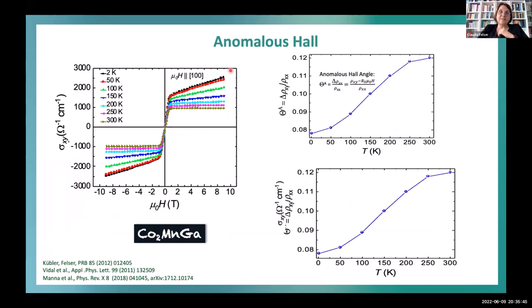So we have this linear kind of behavior here, and here we have the resistivity rho xy versus the magnetic field. And from the first view, it looks like a hysteresis, which everybody has probably already measured in something like iron in a SQUID. So you see this hysteresis loop, and it's a soft magnetic material, so we don't really have hysteresis. It's very soft, the Heuslers, because they are cubic. And you have this normal contribution to the Hall effect, but this jump here is coming from the anomalous Hall effect. And since it looks like a SQUID measurement, everybody believed it goes with magnetization.